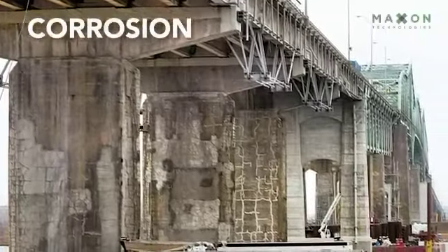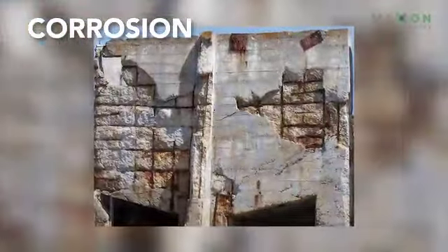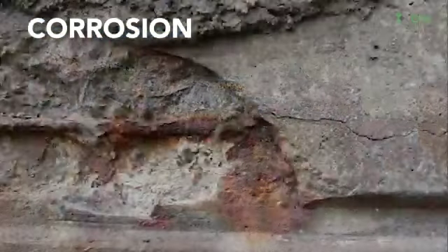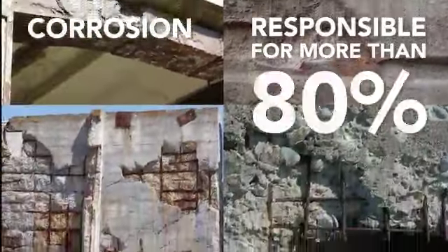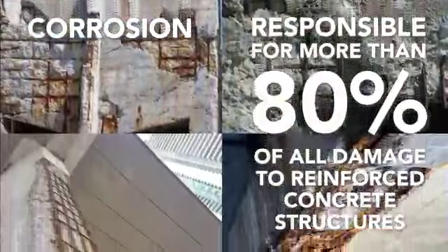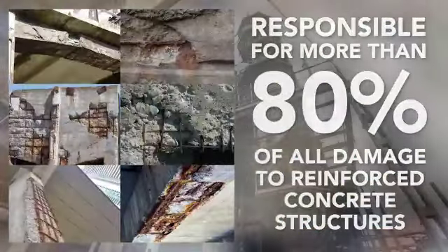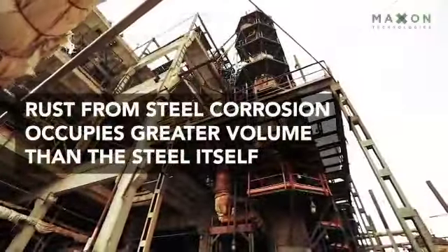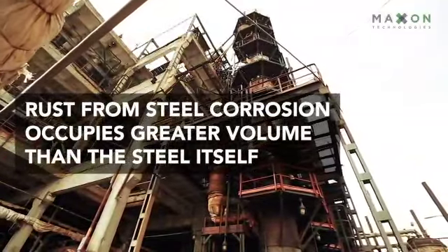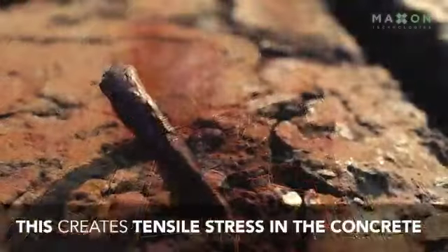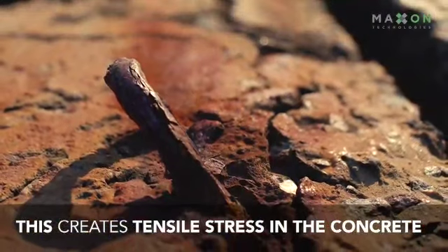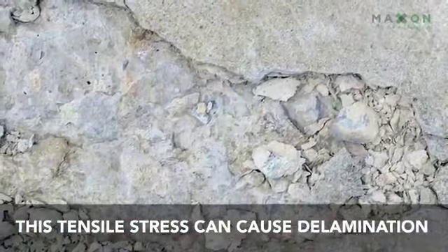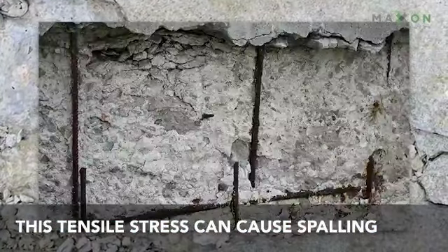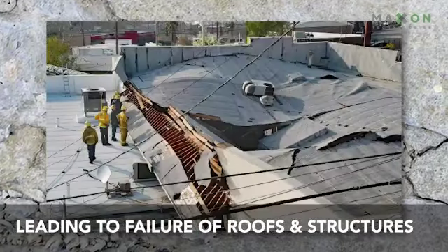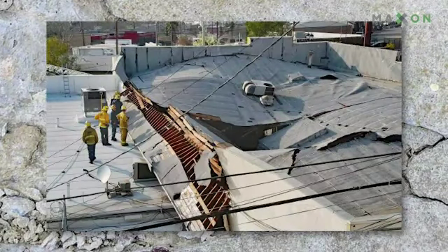Corrosion in concrete gained worldwide attention at a recent ACI convention, where findings showed that corrosion is responsible for more than 80% of all damage to reinforced concrete structures. When steel corrodes, the resulting rust occupies a greater volume than the steel itself. This expansion creates tensile stress in the concrete, which can cause cracking, delamination, and spalling, eventually leading to the failure and collapse of roofs and structures.